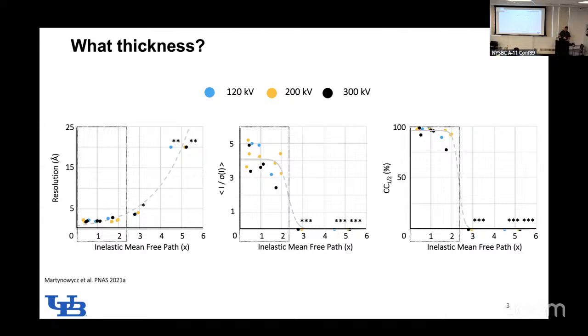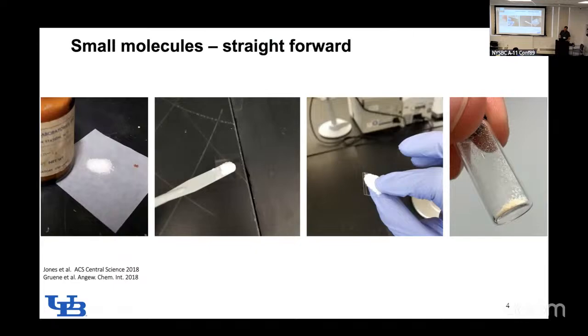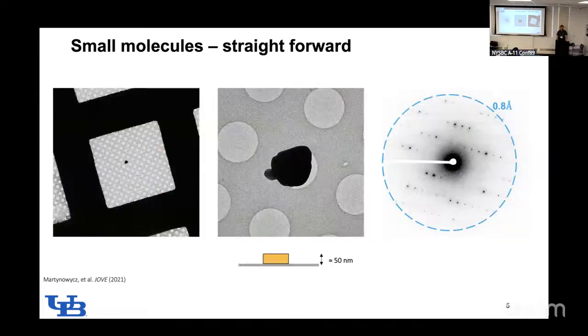But the takeaway from this is please hope you have crystals that are smaller than 600 nanometers thick on average. For some samples, this is pretty easy, for small molecule samples. We can look at Tim and Chris Jones's papers that came out in 2018. This was done before, but this is when it got popularized. You could just take some powder and grind it between some glass slides, put this on a TEM, and you will naturally have these crystals that diffract to atomic resolution and are thin enough already. Nothing has to be done. It's relatively simple.